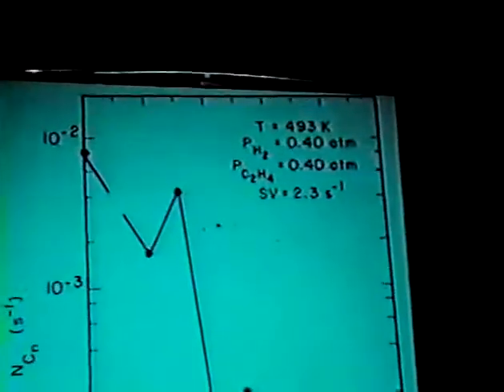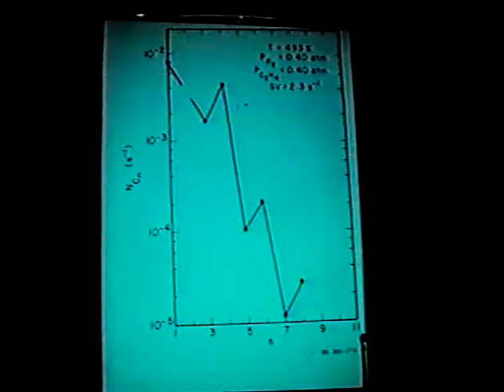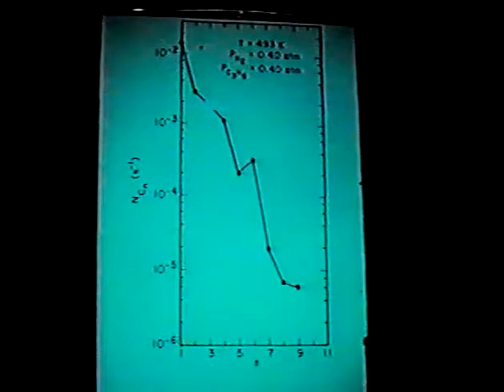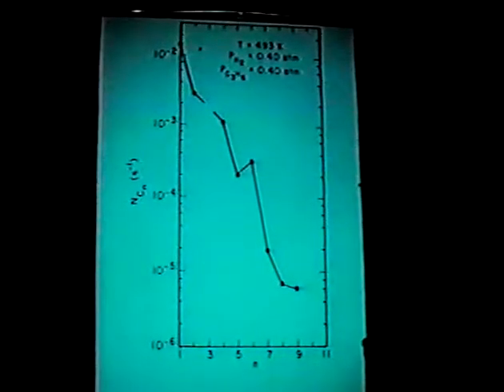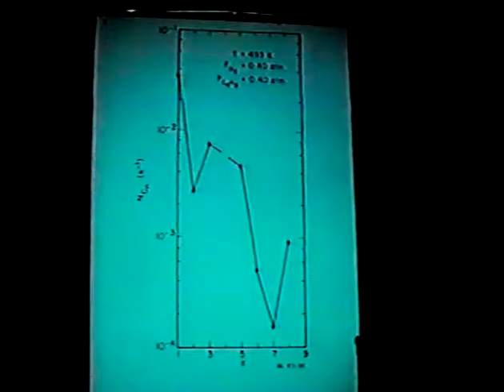I'm going to go through a series of experimental slides fairly rapidly here just to give you a flavor for these results. Here we see the results of adding olefin ethylene by itself with hydrogen. This is a background experiment. And we see a staircase with zigzag type of product distribution, which is indicative of chain growth, homologation by C1 and C2 intermediates. If we use propylene as the additive, we have an even more interesting product distribution, again to be characterized by incorporation of C1, C2, and C3 intermediates. For butene, C1, C3, and C4 give an even more complex kind of product distribution.